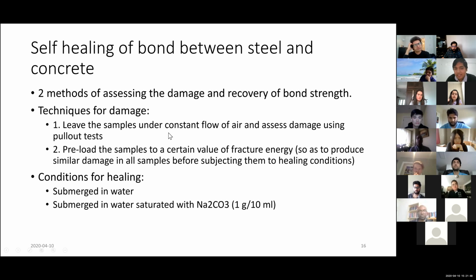Once again, I can leave these dog bone specimens with one fiber in between and leave them under a constant flow of air and assess the damage again. Or I could preload the samples up to a certain value of fracture energy so as to produce a similar damage in all of those samples, and then this can be introduced as a damage, and then they can be tested again for self healing. So basically the rest of the healing part stays the same. One will be submerged in water, one in sodium carbonate water.